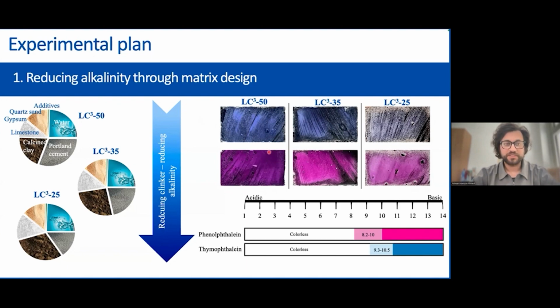Now, to see the effect on the alkalinity of the matrix, on the right-hand side you see some of the samples that we prepared. We cut them, and on one face we spray thymolphthalein, the top one, and the other face of the same sample we sprayed with phenolphthalein indicator. Here you see how the color change works with these two indicators. Phenolphthalein shows a light pink color between pH 8.2 and 10, becomes darker above this range, and remains colorless below it, while thymolphthalein has a slightly higher but overlapping range, showing light coloration between 9.3 and 10.5, dark coloration beyond this, and remaining colorless below.